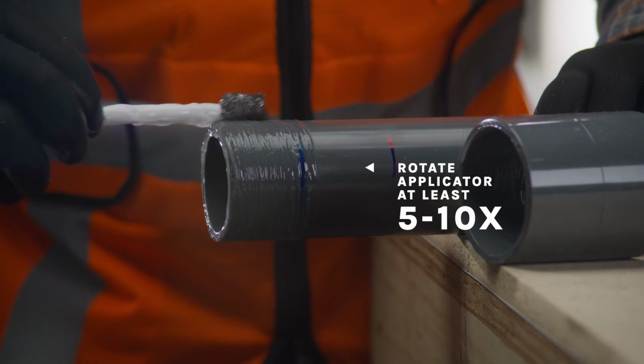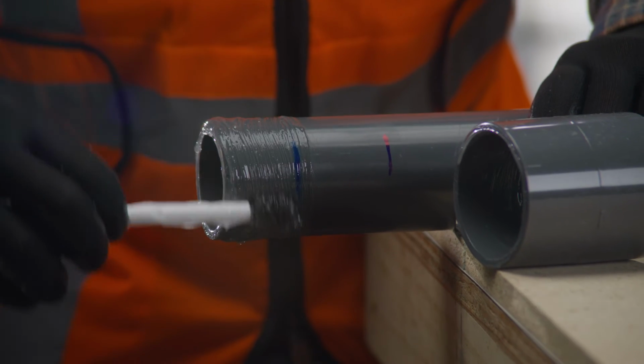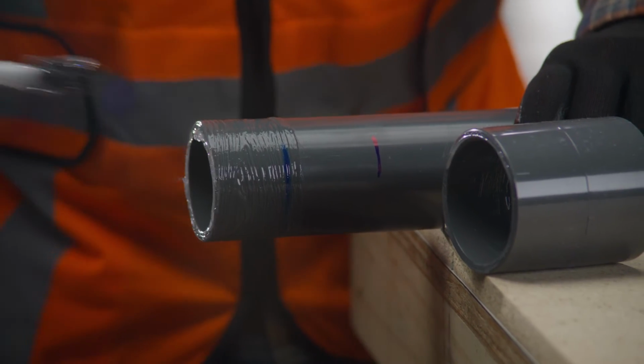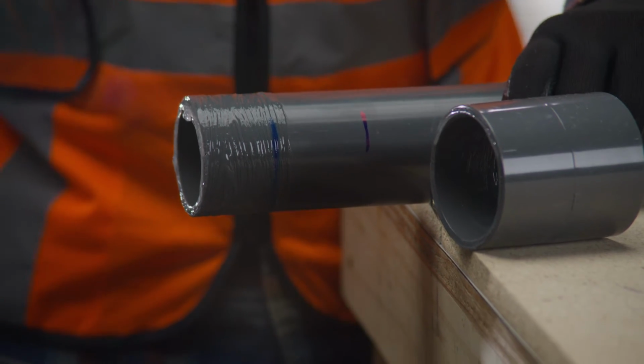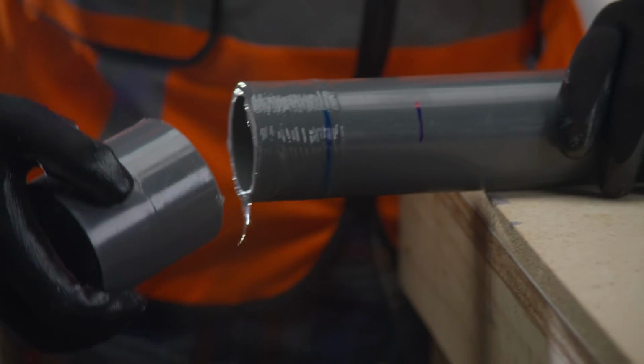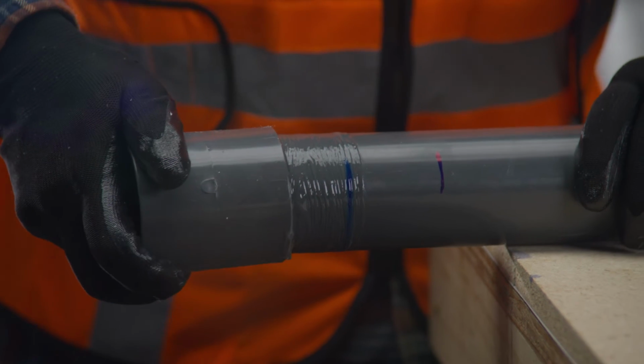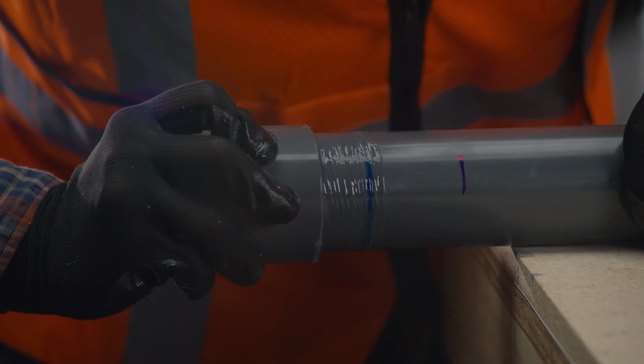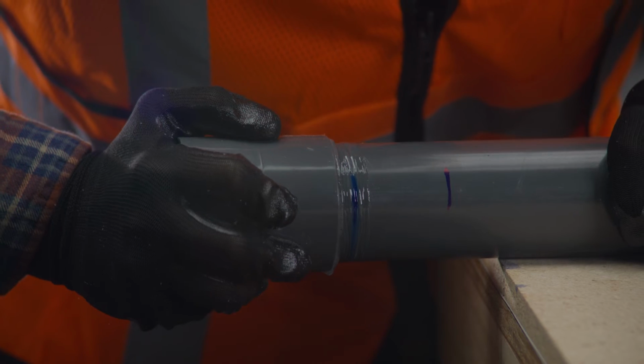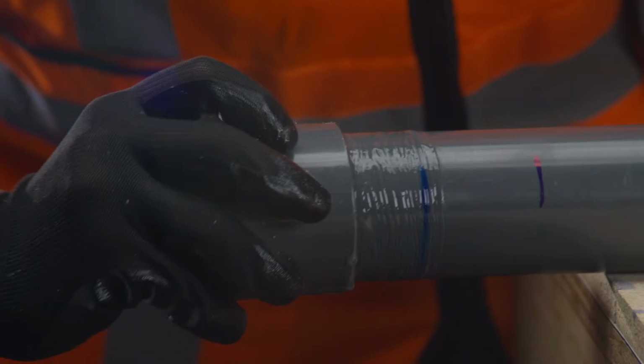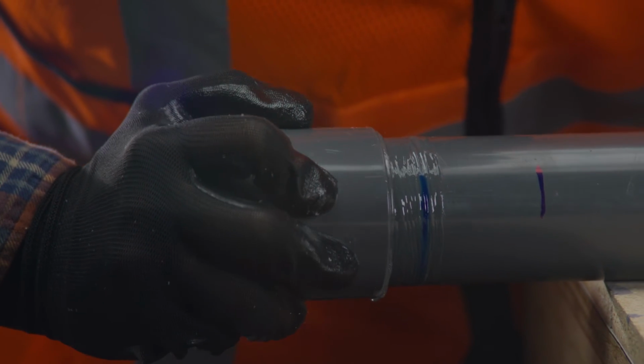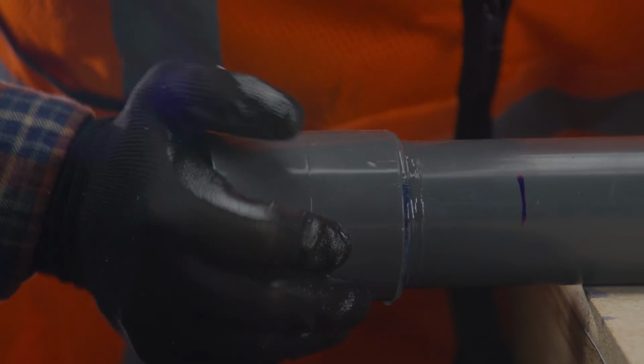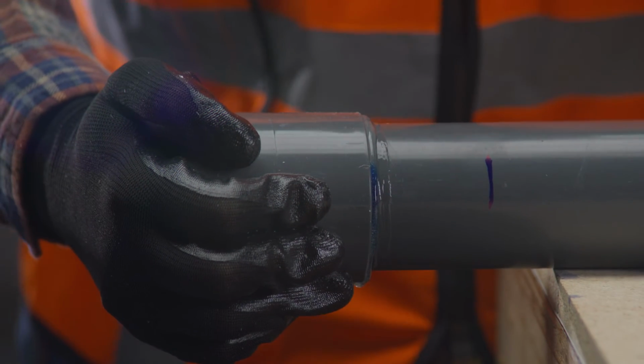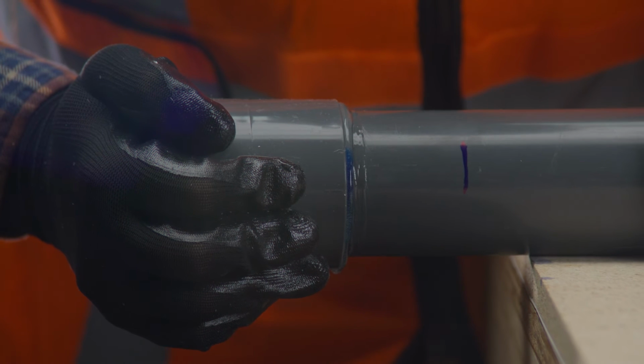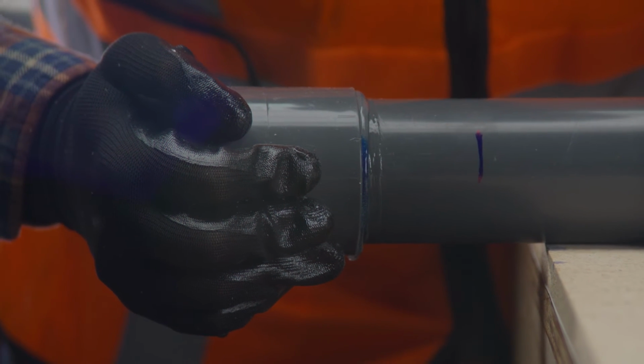Most joint failures are caused by insufficient application of cement. Again, do not let the cement run down the inside of the fitting or pipe. Working quickly, assemble the pipe and fitting while the cement is still wet. If it's not completely wet, recoat before assembly. Push the fitting onto the pipe and rotate it an 1/8 to 1/4 turn until it reaches the pipe stop. Do not continue to rotate the fitting after the pipe has reached the socket bottom.